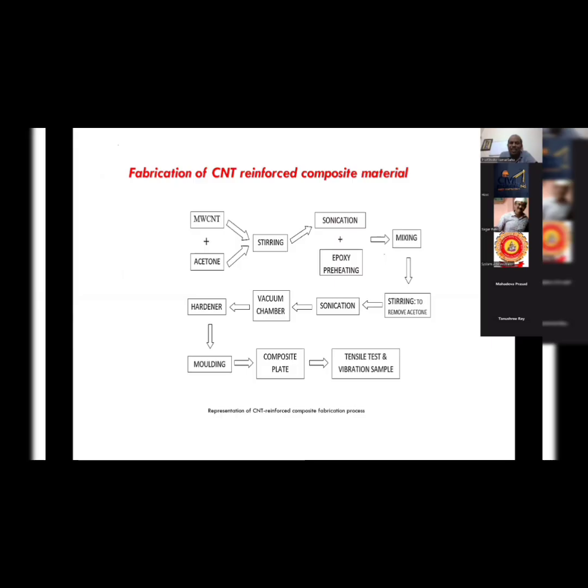Fabrication of CNT reinforced composite material. This is the first, multi-wall CNT. We are using multi-wall CNT plus acetone. Then we do stirring. Then sonication is done. Then it is added to epoxy, preheating, then mixing, then stirring. Then again sonication, it goes to a vacuum chamber and hardener is added. Then molding is done, composite plate, and then tensile test and vibration samples are prepared. So right now this test is going on.